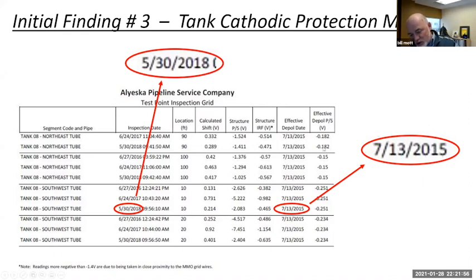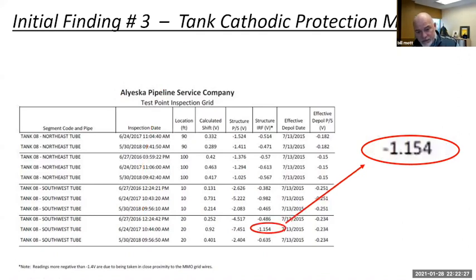The depol readings change over time due to moisture content, due to temperature, due to soil chemistry, and actually the application of CP impacts the depol reading. So the fact that you have a CP system on will change this reading, which is why you have to collect it at essentially the same time as your instant off reading. That's why the code or the standard requires you to measure that formation or decay. And that's not what's being done.